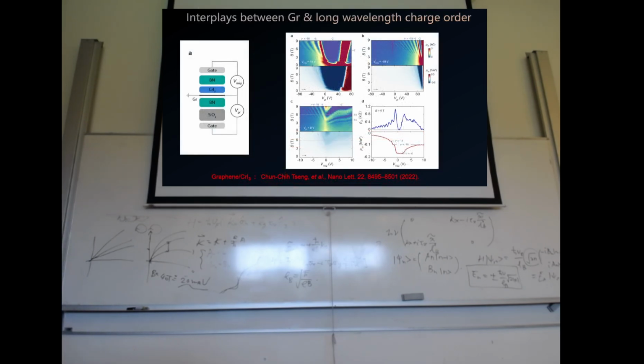One is the chromium triiodide, and the other is our system, chromium oxychloride. So this is the other system published in 2022 in Nature Nanotechnology, from Washington University. What they saw is another system. Instead of using hBN, they use chromium triiodide, and then the graphene is showing very similar behavior as our system, but the data quality is somehow a bit lower. But you can see that the quantization happens at a lot lower magnetic fields compared to the conventional phase. That means the effect is universal. It can be repeated in different systems, and in our system, we managed to understand that.